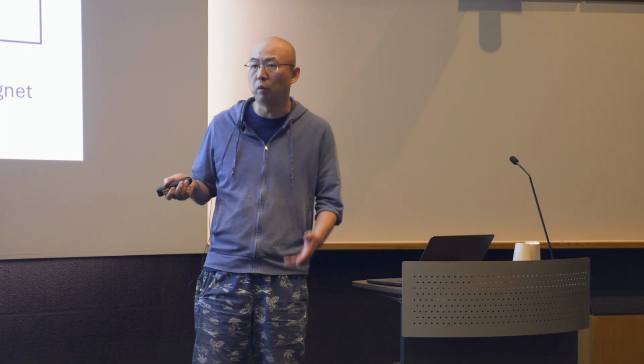Now, if you want to get a spin liquid phase, you need to stay very, very close to the disorder-free limit. And we know now that this number should be less than 1% doping, and preferably 0.5% or less. That puts a lot of stress on experiments: we need to grow crystals in extremely clean conditions in order to see the spin liquid phase.